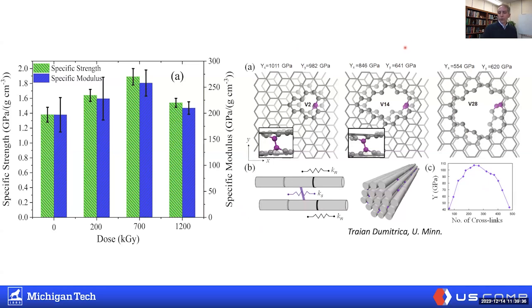So Traian Dumitrica at the University of Minnesota and his team developed this multi-scale model, a molecular model on the top, a mesoscale model on the bottom, where the idea is we actually look at the defects. So when a gamma ray comes in, it knocks out some carbon atoms, and it also creates bonds that weren't there before that are now formed. These are the crosslinks. And so we could take a look at the different types of vacancies that we create, and we could get a good idea of how these bonds form.